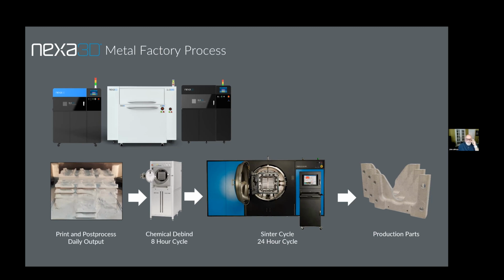Once the prints are complete, we take what we call green parts out of the machine. They go through a chemical debind, which will remove part of the polymer backbone and create micro cavities in the part. Those microcavities are crucial in the next phase of the sinter furnace because as that metal expands, there's room for the metal to expand within the part without creating distortion and twisting. So the result is we get very accurate production parts with very high degree of density and, compared to CNC machining, very high mechanical properties. Also, of course, no supports, and we're working in a zero waste solution. So fantastic.